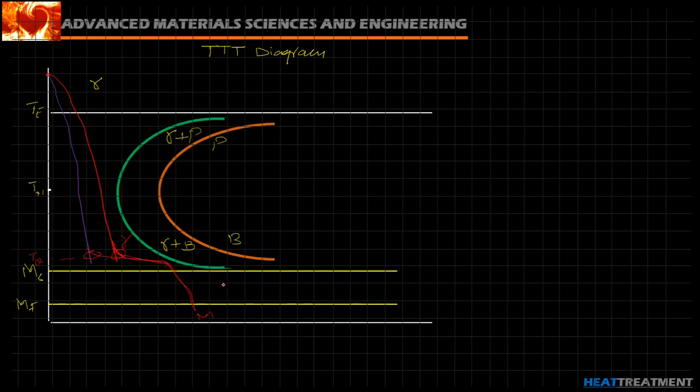And if we consider the inside and outside cooling curves, we interrupt the cooling before the start of the martensite.